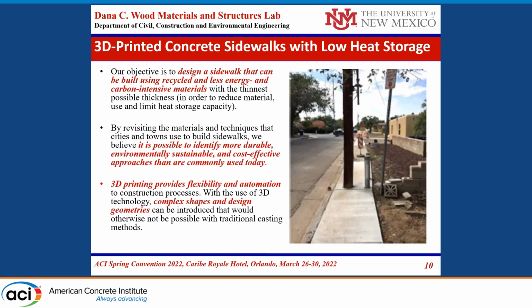One of the reasons we looked at sidewalks, by the way, is the strength demand on sidewalks. I believe that we can make sidewalks with strengths in the 1,000 to 2,000 psi range. You don't really need a very high strength concrete. Sometimes we say the standard 3,000 psi concrete is good for the sidewalk. Actually, it's very strong. You might not need this much cement material. And if you see what the main problem in sidewalks is, it is shrinkage cracks. So if we can reduce the cement, we might have sidewalks that are more durable and more sustainable.